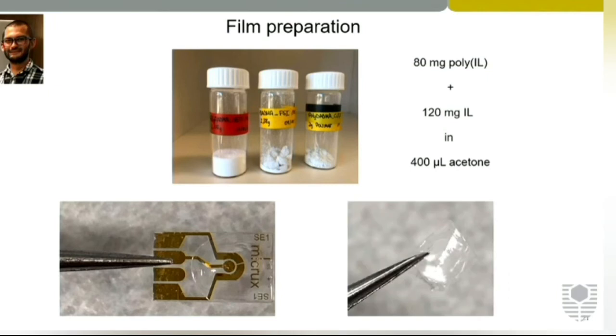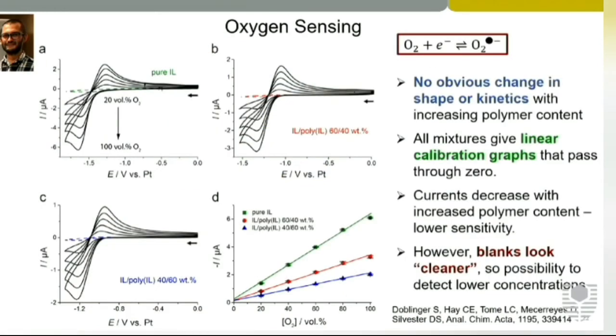And these are really interesting materials. They're much better than the normal mixtures of polymers and ionic liquids, because they're actually really peelable. So I've got a couple of students working on peelable films to pick up solid explosive materials or solid materials on surfaces, and then bring the material directly to the electrode by taking the side which was swabbed straight to the electrode. In terms of gas sensing, though, they actually behave really nicely.